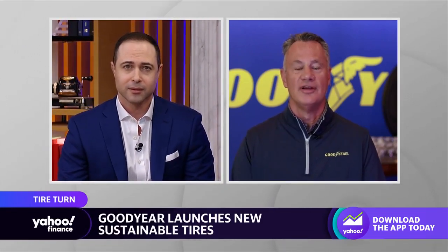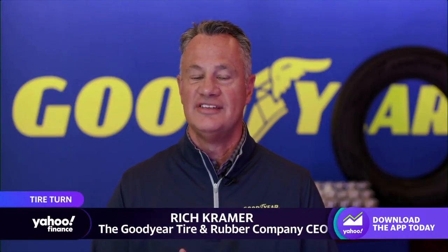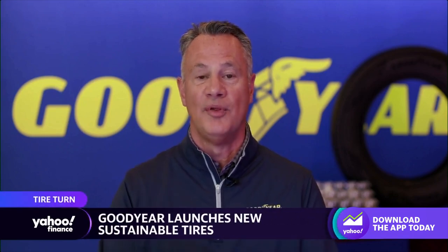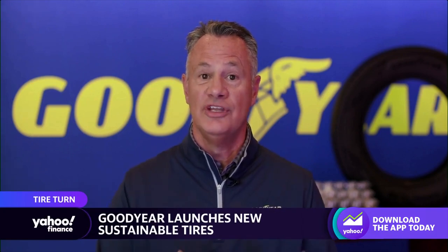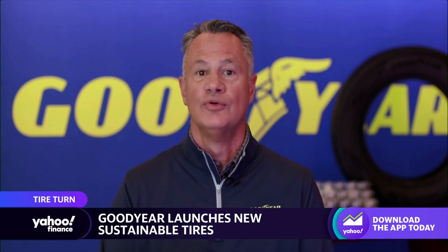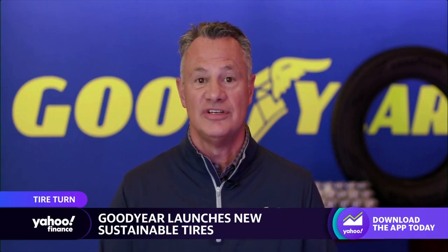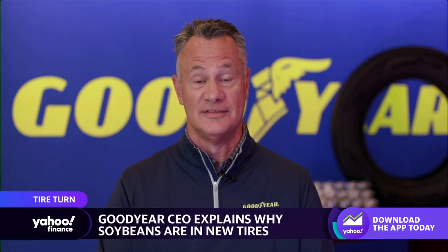Well, Brian, you're exactly correct. So those two materials, I've got to give credit to the team for coming up with this. Both of those actually don't degrade performance at all. They actually increase it. In fact, soybean oil makes a tire more pliable in cold conditions. It gives it more grip. And rice husk ash, we use as a replacement of petro-based silica, and what that does for us is actually improve rolling resistance on the tread. So this is a way of moving to those bio-based materials and not giving up any performance. And in fact, in many cases, enhancing performance.